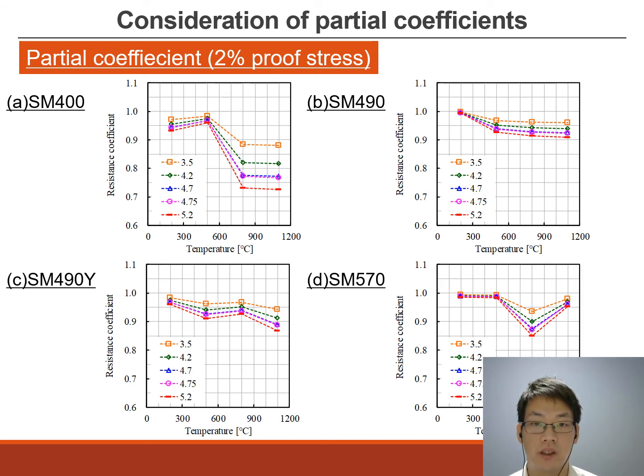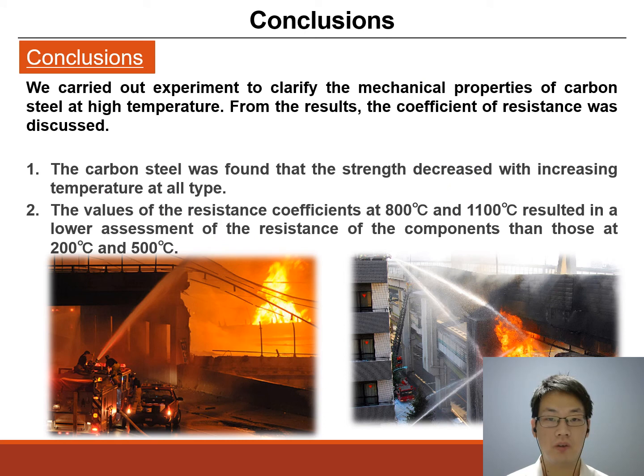Next, the result of calculations of the resistance factor at 2% proof stress are shown. As can be seen, the result shows the same trend as for the 1% proof stress. I'm about to wrap up my presentation. We carried out experiments to clarify the mechanical properties of carbon steel at high temperature. From that result, the resistance coefficient was discussed. The conclusions obtained from these studies are summarized as this.